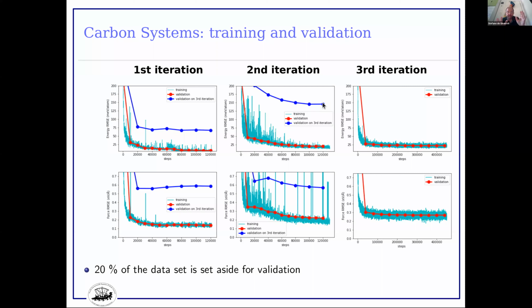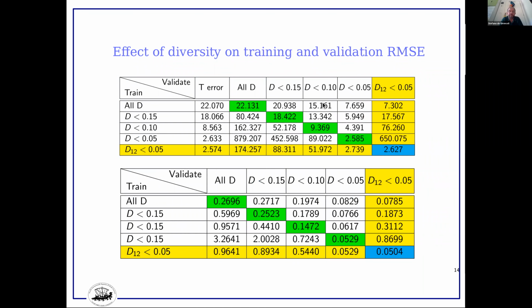Okay, I skip. I come to this table, which is in numerical form. It tells you the concept that I was trying to make, the take-home message. Okay, the top table is the energy per atom, the error in the energy. The bottom table is for the forces, but the message is the same. If we train on the full data set, at the end we have a training error of the order of 22 meV per atom. And if we validate on a set of independent configurations, but taken from the same distribution, we get a similar error.